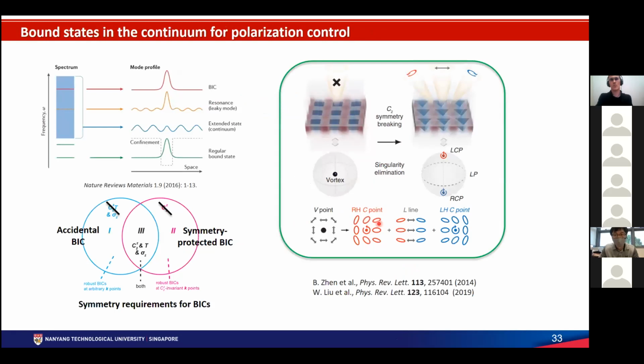We continue to investigate the ability of BIC to control the polarization distribution in the far field by now breaking the in-plane inversion symmetry. If you break the in-plane inversion symmetry, the integer charges that are associated with BIC will break into 2 half-integer charges, each of them associated with perfectly circularly polarized emitted light.